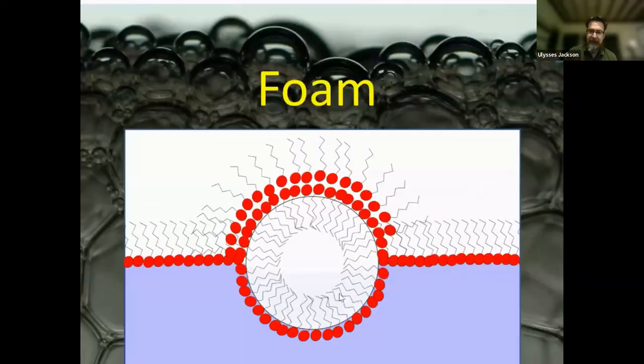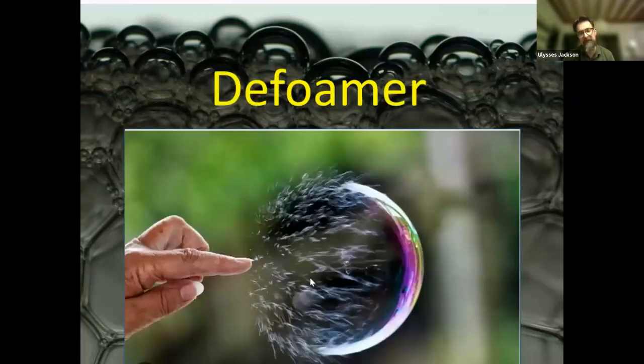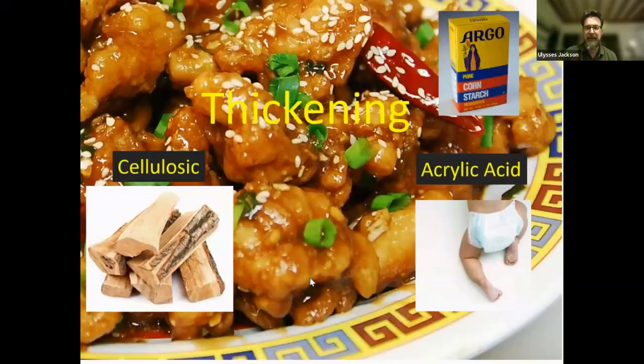So surfactants are great. So why not add a lot of them? And the reason is if you add too much, you get foam, right? So here we've run out of solids, and you can see the surfactants formed a double layer, an air bubble, which could be a real hassle. So to combat that, we're trying to always balance our surfactant load, but also we add things called defoamers that are like molecular needles that come in and disrupt that micelle, much like that finger is rupturing that ball. It allows the air to come out, bubbles to come together, and to leave the system. And then we also use de-aeration equipment.